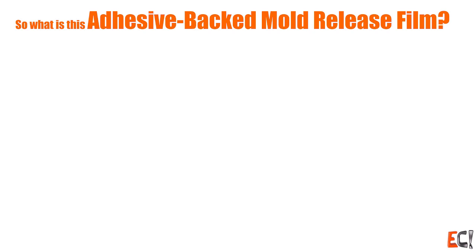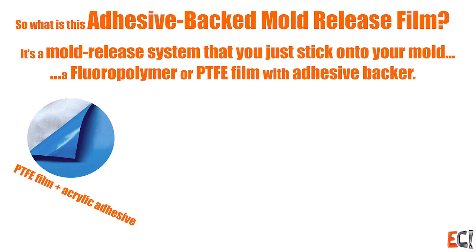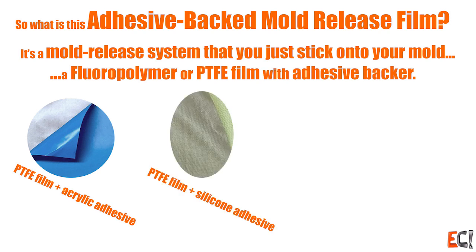So what is it? It's pretty much just a sticker with Teflon PTFE fluoropolymer film with a pressure sensitive adhesive backer. It can be a PTFE film with an acrylic adhesive, which is cheaper but really only good for one use, or a PTFE film with a silicone adhesive of varying thicknesses, which can be peeled off again and patched. It's about twice as expensive.